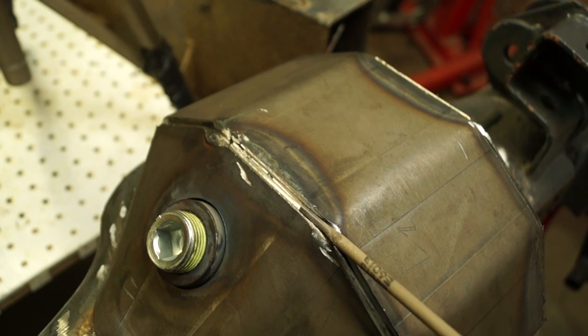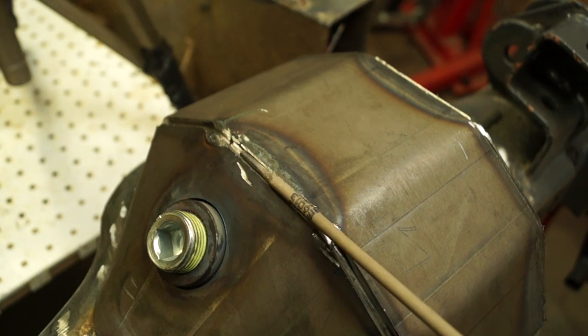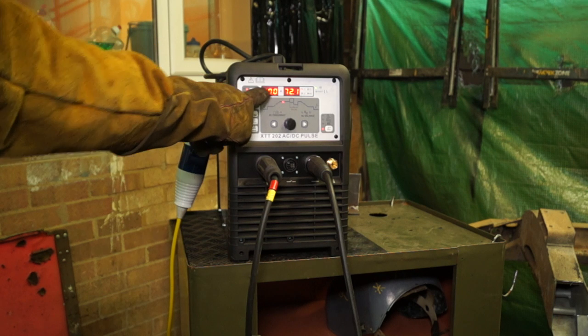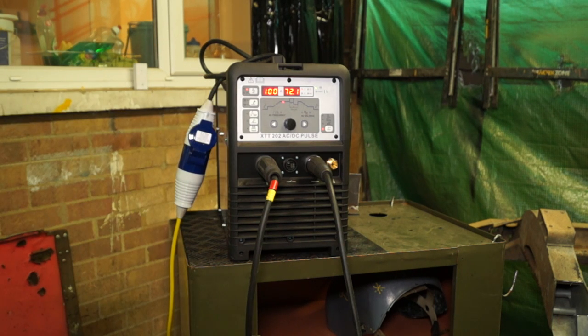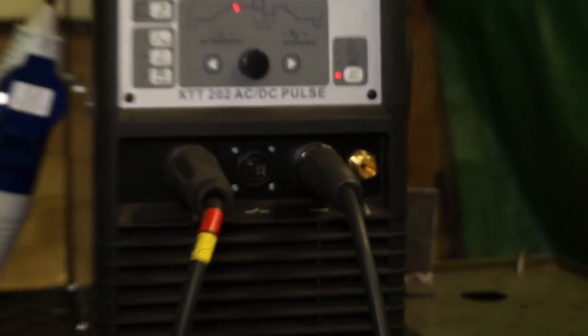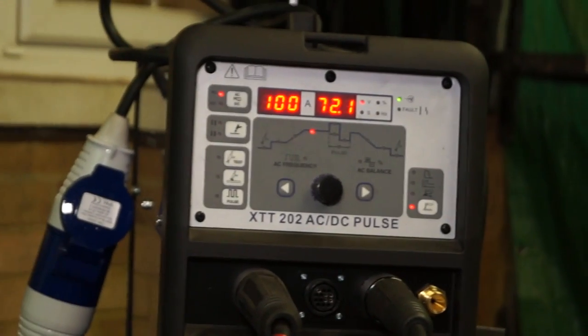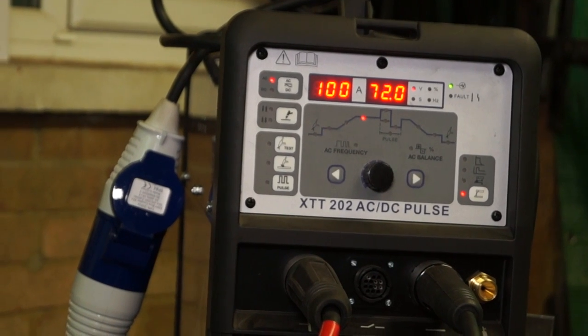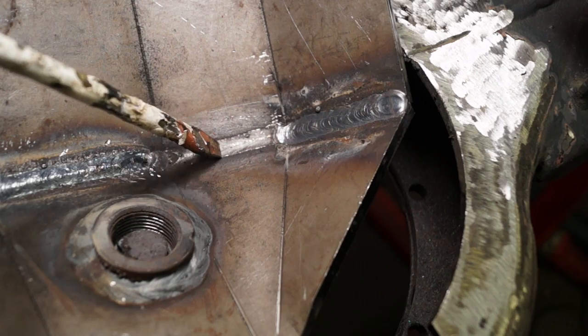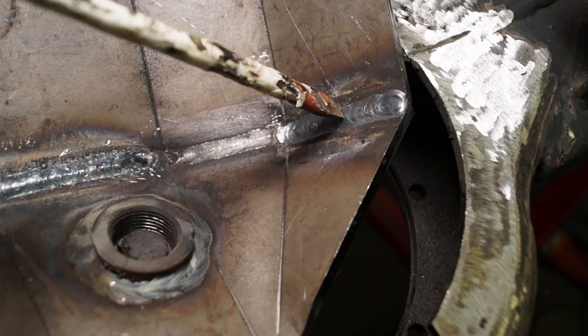The stick I'm using is 3.25, and the amperage is about 100 amps. I don't know if you're surprised at that, but actually that's a little bit too hot. And I'll just take it up there. It's actually on AC, AC positive, electrode positive. Now that's the TIG weld, and this is my weld here.